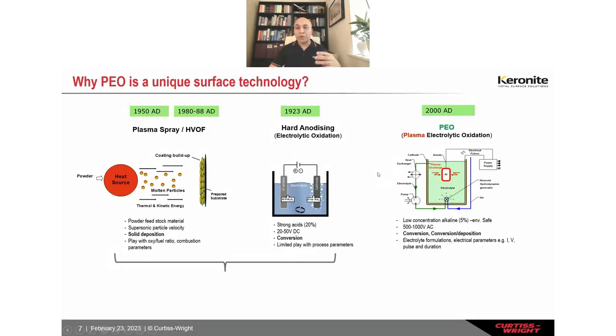Here on the PEO process, what you do is you apply extremely high voltages, in excess of 500 up to 1000 volts. And by applying the high voltages and high electrical field, you generate plasma on the surface. That is the essence, the fundamental of the PEO. You generate plasma on the surface, and hence plasma electrolytic oxidation, or PEO.